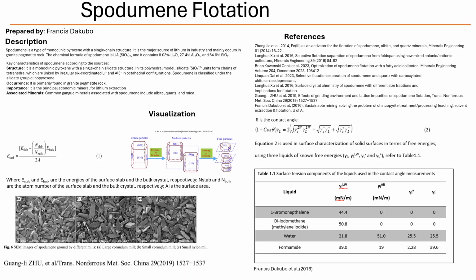CCS. Carboxylated chitosan. It's derived from chitin, from shellfish shells. Seriously, chitosan in mining? Yeah. The thinking is the carboxyl groups on the CCS molecule can chemically bind quite strongly to spodumene, potentially blocking collector adsorption there if used that way, or potentially binding weakly to quartz to depress it. The study suggested it chemisorbs onto spodumene, but has weak adsorption on quartz, making it a potential selective depressant for quartz. It's quite specific chemistry. That's fascinating, using natural derivatives.